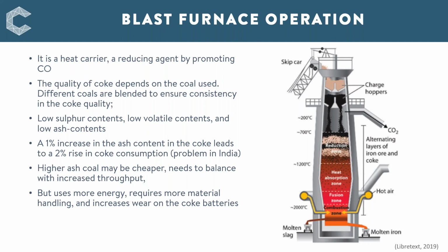In the blast furnace here, they've got a schematic diagram on the right, and coke serves several purposes here. It's layered with iron ore and limestone, and the coke acts as a heat carrier and as a reducing agent. The coke is fed by gravity into the layers, and the high temperatures at the bottom of the blast furnace are ignited either using pulverized coal injection or gas or oil to sustain heat, which forms CO2, which then reacts with more coke to form carbon monoxide.